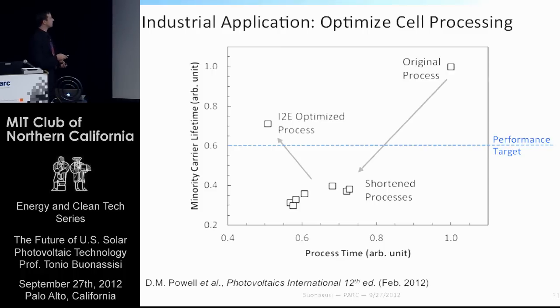The original process was up here. The shortened process, just guided by intuition alone, dropped the performance of the material. The minority carrier lifetime decreased below the performance target, so it was not viable for commercial application. But the process was much shorter. We continued working, optimizing the simulation code until finally we were able to further shorten the process time while improving the electrical performance of the material, and resulted in a process that meets the performance targets and is less than half of the initial process time. And this allowed a company to take a new product to market. We're very proud of that.